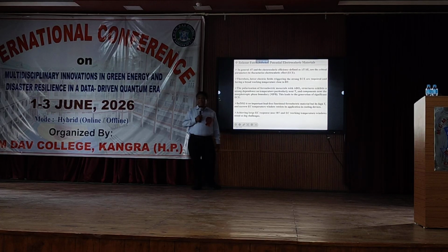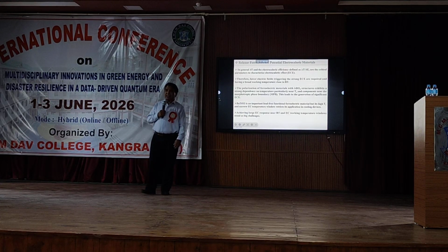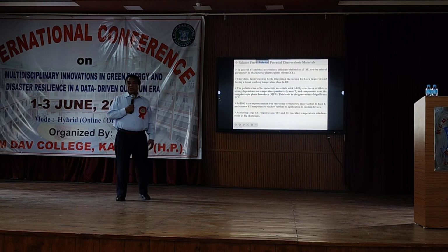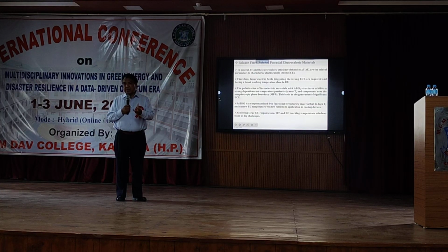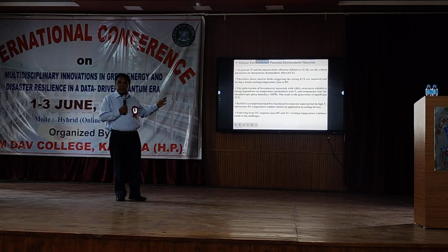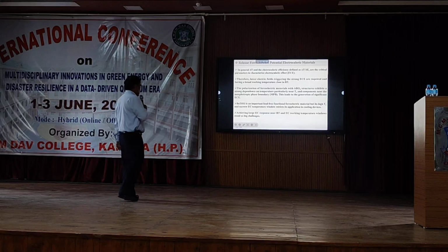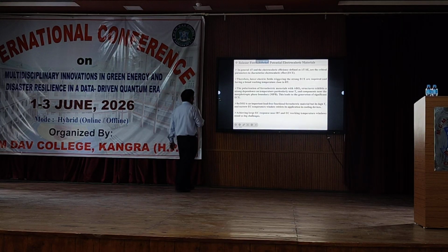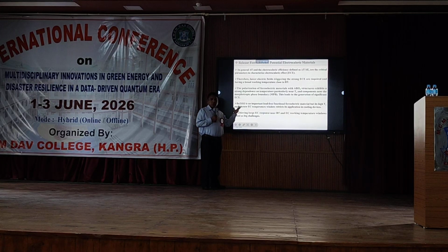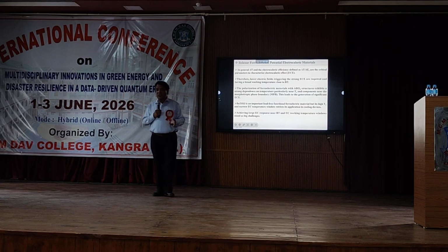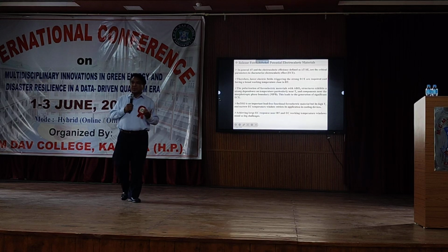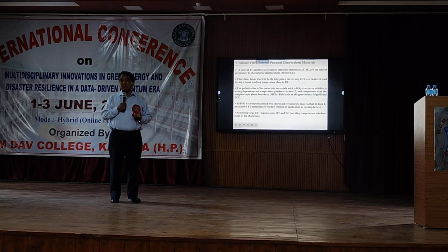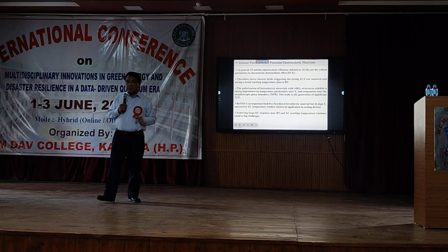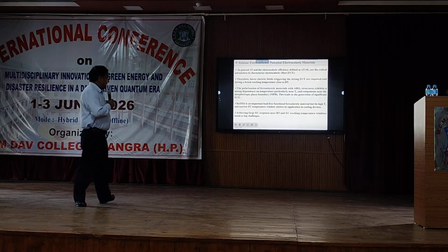And then it is not delta T, rather efficiency of cooling is defined as the ratio of delta T and applied electric field. So if some material is having significant change in the temperature under low applied electric field, then that material will show the high efficiency of cooling. And morphotropic phase boundary is again very helpful to get the high polarization value, and temperature dependent polarization is huge at the Curie temperature. So if we bring down the Curie temperature near the room temperature along with morphotropic phase boundary formation in the material, that material will be very helpful for enhancing electrocaloric effect.